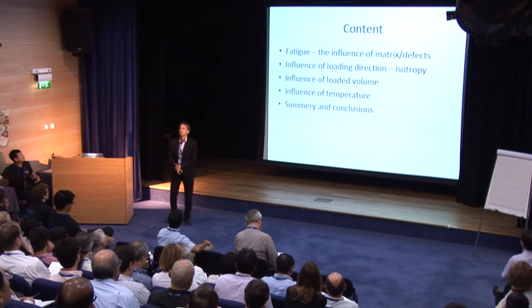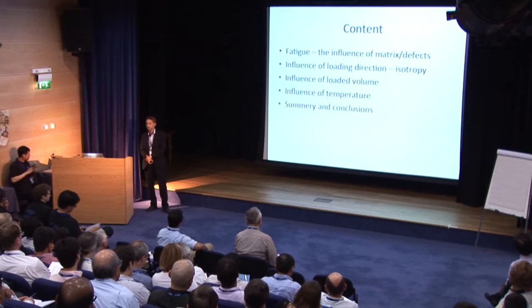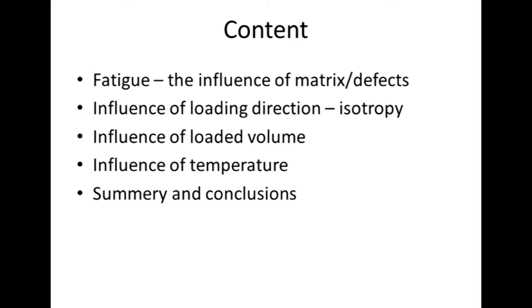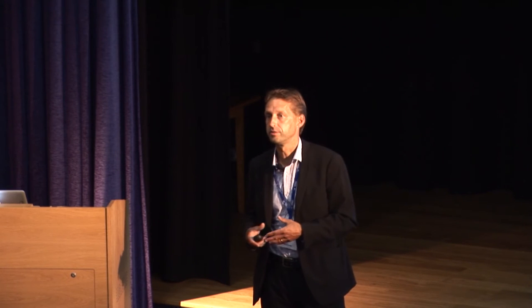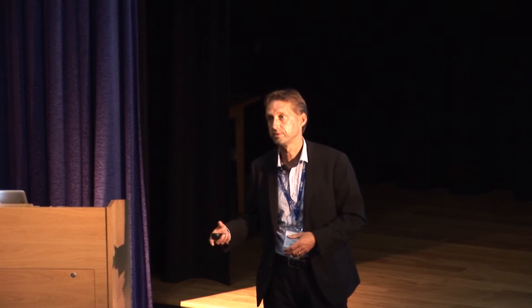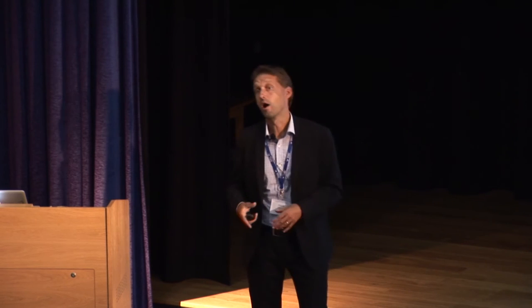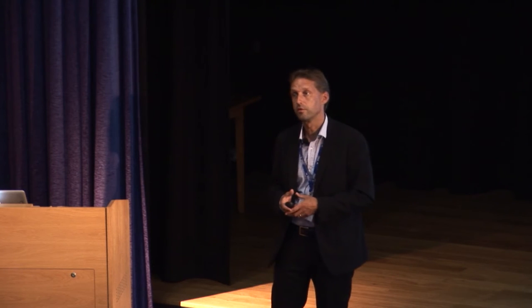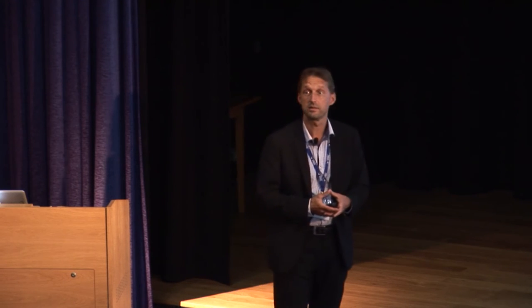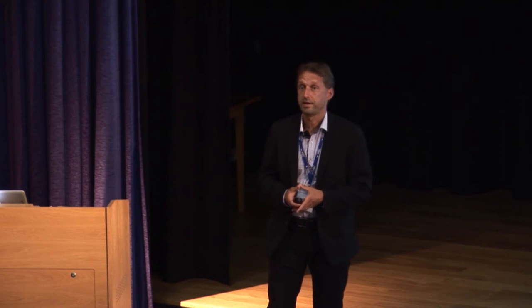I will start by talking about fatigue in general, in terms of the influence of both the matrix and the defects. This is really something that we have experienced. It's very important that we think about those two different mechanisms. What is really controlling the fatigue? Is it the matrix, or is it defects? Could we change the matrix in order to accommodate a feature better? Is one microstructure better than the other? I know there are differences, because we have seen that, and those kinds of discussions are very important to raise, and we should put more effort into investigating them. But also, of course, the defects, because they are there, and we need to consider them.